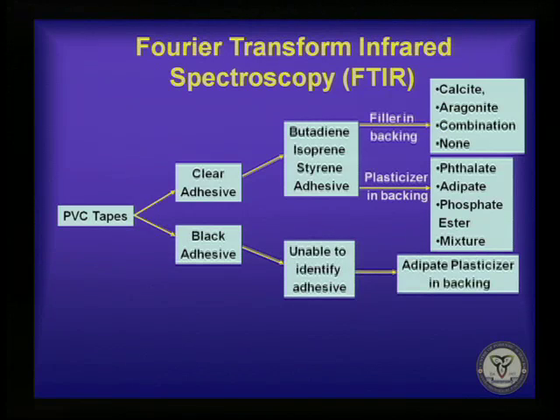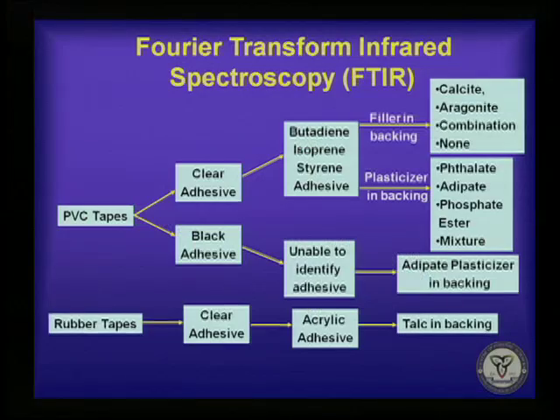The black adhesives, due to the high loading of carbon black, it was difficult to identify the type of adhesive, but we were later able to identify the adhesives using pyrolysis gas chromatography, and all of these had adipate plasticizers. Four of the samples that we had, manufactured by 3M, were rubber-backed tapes, not PVC-backed tapes. These ones had clear adhesives that were acrylic and talc in the backing. We were not able to further discriminate these four tapes chemically. One tape had a different width, so I'm going to focus my discussion on the PVC tapes.